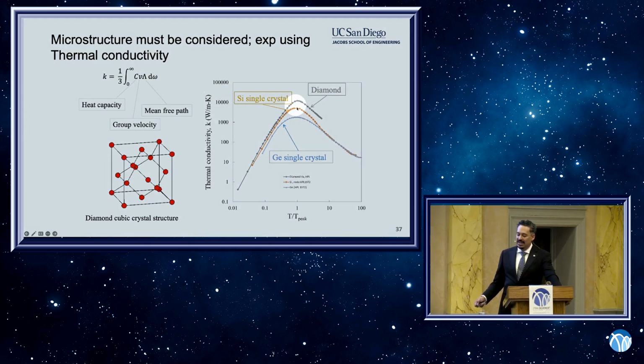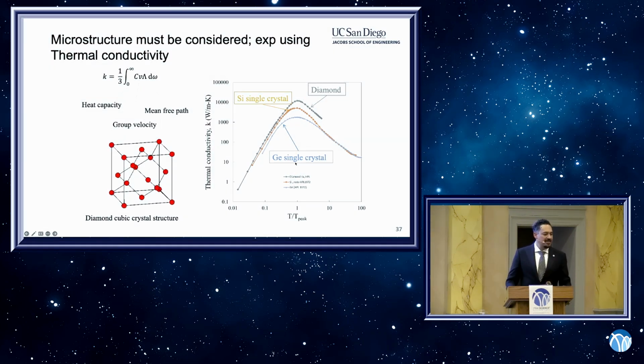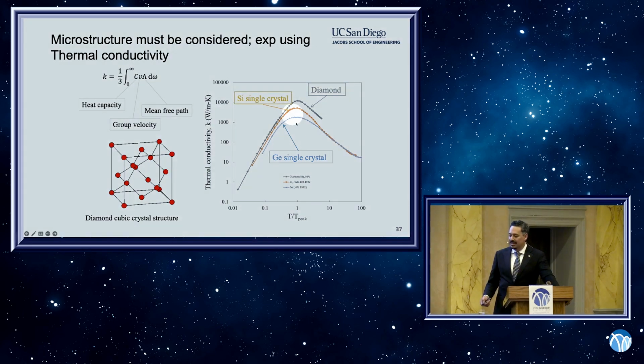And finally, the magnitude, so why diamond is a higher thermal conductor than silicon and germanium, can be understood by the last thing, which is the group velocity. So in diamond the atoms can vibrate the fastest. So they have this high group velocity. So it's the highest thermal conductivity. Silicon is heavier, so the vibration is slower. So you get silicon in the middle. And the heaviest element here is germanium, having the heaviest and lowest frequency phonons, and that's the lowest thermal conductivity there. Okay, so that still doesn't take into account microstructure.